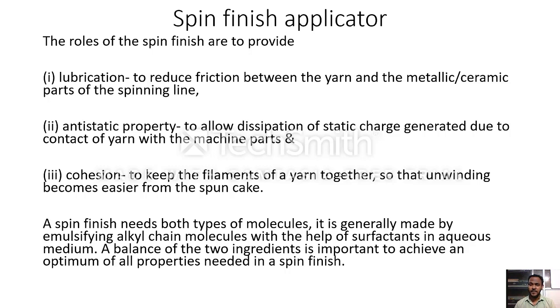Because of the presence of hydrogen bonding, you get the anti-static property, and because of the presence of aliphatic or alkyl chain molecules, that is hydrophobic in nature. It is like a softener where both the hydrophilic and the hydrophobic parts are there. The hydrophobic part is the one which gives the lubrication like an oil, and the hydrophilic part will like water, so that the static problem, the charge generation problems, are removed. So you keep a balance of both the hydrophilic and the hydrophobic components in the spin finish chemical, so that you will get all the lubrication, anti-static and cohesion properties.